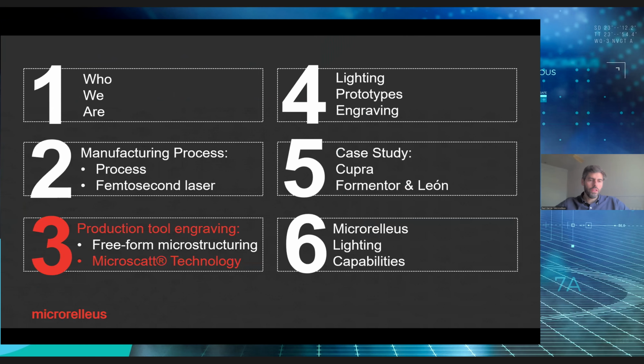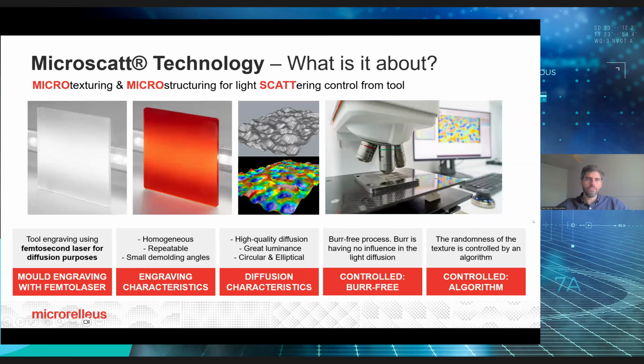So continuing with the production tool engraving, but in this case texturing, we have this Microscatt technology, which is micro-texturing, microstructuring for light scattering control from the tool. We are engraving the mold, and by injecting transparent material, you can control the diffusion of the light. The two parts on the left are transparent material injected, but as you can see, they have this milky, nice finishing, and we are avoiding the hot spots of the LEDs behind just by the engraving on the tool.